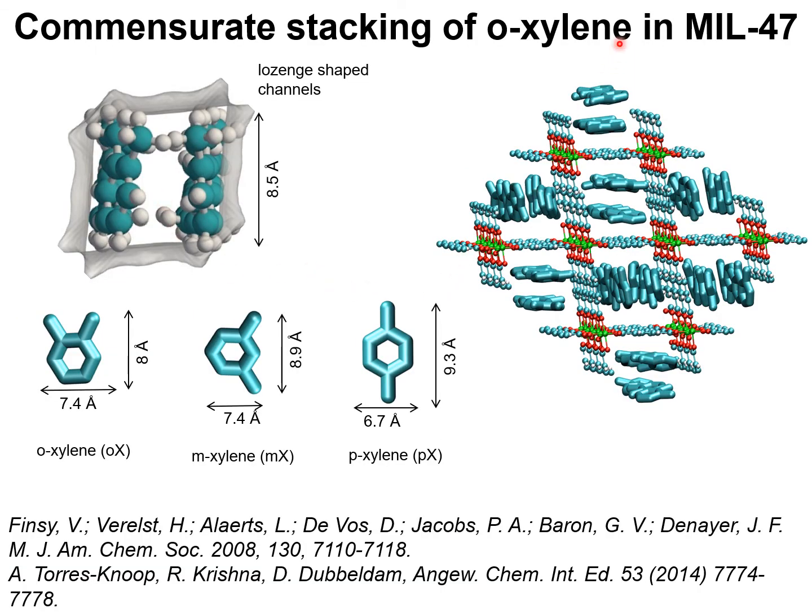Within the one-dimensional channels of MIL-47, that is channels of 8.5 angstrom that are lozenge shaped, ortho-xylene can be stacked because the dimensions are commensurate with the channel dimensions.